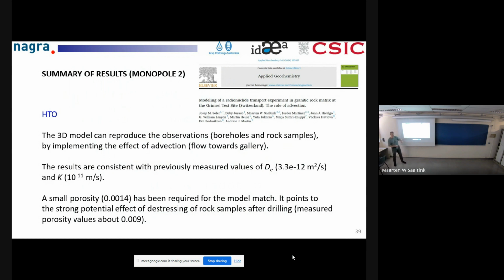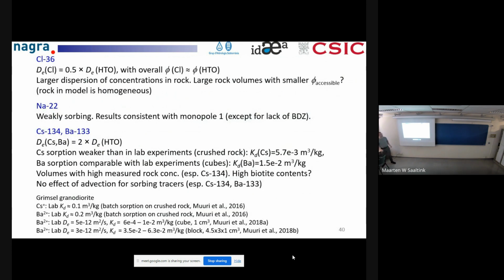However, we needed a very small porosity. That was a big difference. The measured porosity of rock samples from that same area is about 1%, 0.009, and we need values of 0.0014, pointing to unloading and destressing of the rock samples. For chloride, the diffusion coefficient is about half the value for tritium. The agreement between measured and calculated concentrations is not so good, and we attribute that to some heterogeneity in terms of pore sizes and porosities, and anion exclusion.